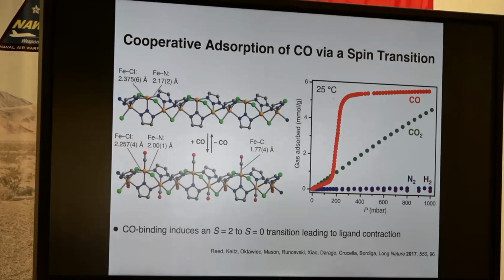And so again, what happens here is iron binds CO. When it goes from high spin to low spin, the iron contracts in radius. That destabilizes neighboring irons. They also want to contract. They also want to bind CO. So it's an all or nothing proposition. You're either binding CO and going low spin, or you're not. This is just coincidence, but if you model that step with the Hill equation, you again get an exponent of n equals 11.